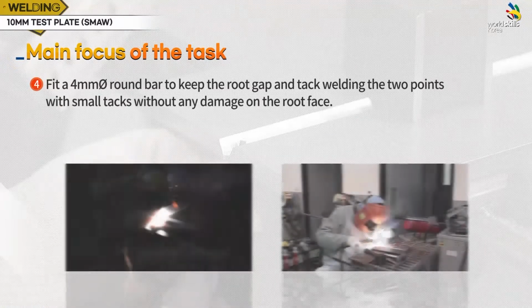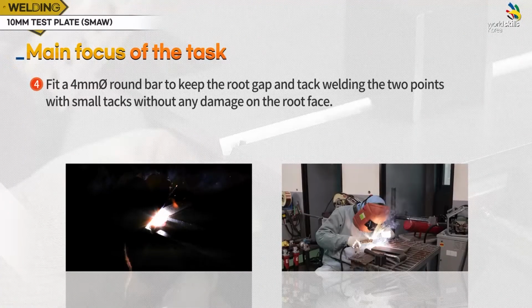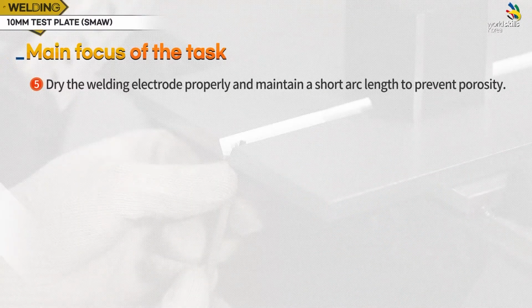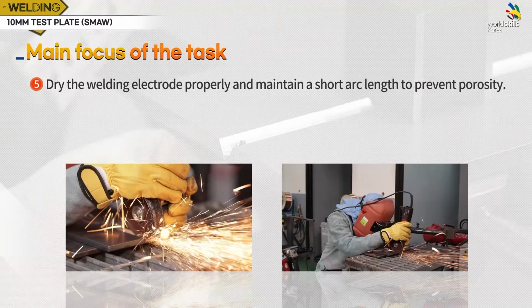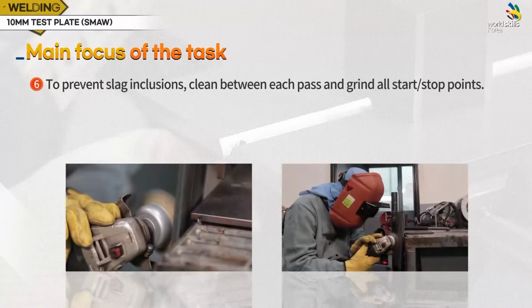Fit a 4 mm round bar to keep the root gap and tack weld the 2 points with small tacks without any damage on the root face. Dry the welding electrode properly and maintain a short arc length to prevent porosity. To prevent slag inclusions, clean between each pass and grind all start-stop points.